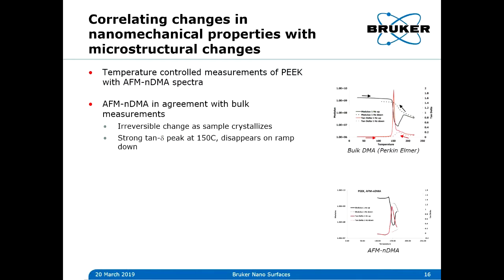Another variable temperature experiment demonstrates that the sample microstructure can affect the mechanical properties of the sample. In this case, the amorphous polyether ether ketone, or PEEK, has a sharp glass transition, but once it crystallizes, the glass transition disappears. So this is looking at the bulk DMA from Bruker here. If you increase the temperature, you see a very sharp peak in your loss tangent, or tan delta, and also your storage modulus drops at the same time. Right. Then what happens is the sample starts to crystallize, and that's indicated by this increase in the storage modulus. And that's without even reaching, you're not melting it. You're just giving the material more mobility by increasing the temperature.